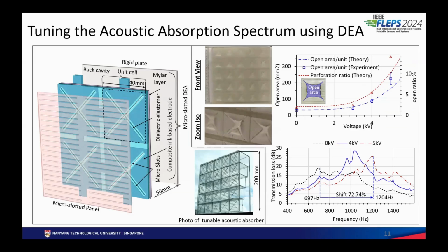And the absorption spectrum of this acoustic absorber at the voltage-off state, that is when this is completely closed, has a peak absorption frequency of around 700 hertz. When we activate the device at 5 kilovolts, the whole spectrum is shifted, and then we have a peak absorption at around 1200 hertz. So we can shift the absorption spectrum by about 70%, and in this way we can get a much broader acoustic absorption.